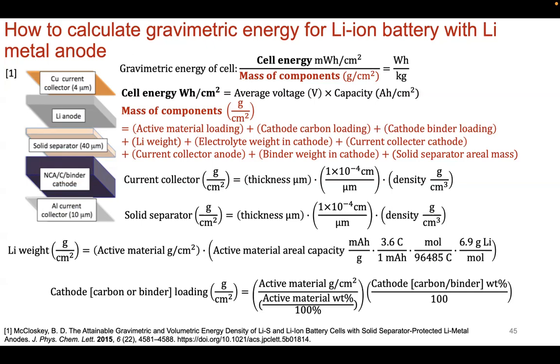So that's pretty straightforward. The mass of each component can be broken down into all the components within the battery. Here you see the copper current collector with a thickness of, let's say, 4 micrometers. You can just go down the list. You can put in the active material loading, how much of the NCA is in the cell. And of course, with electrode design, you don't have just active material, because these are semiconductors or insulators, and thus you need to improve the electrical conductivity, particularly for sulfur as well. So there's going to be some amount of carbon additive added to your cathode. There's also going to be some binder percent included in your cathode composite. The amount of lithium in the cell will be based on the amount of cathode that's loaded. Then there's the electrolyte weight in the cathode, so you have to wet your cathode as well.